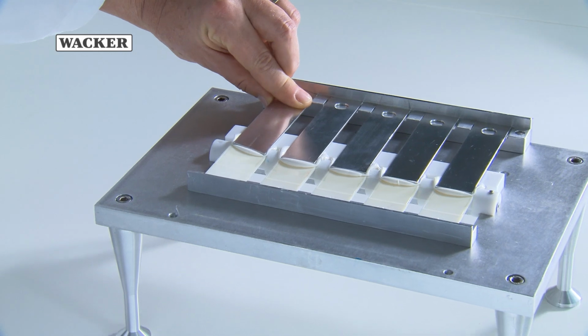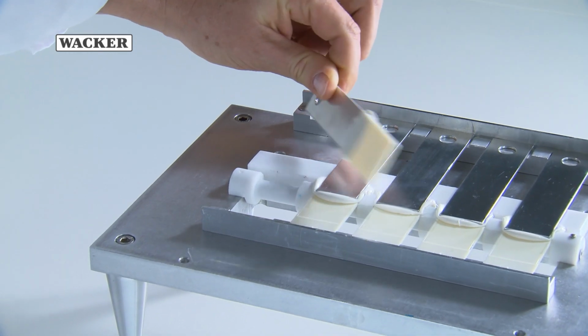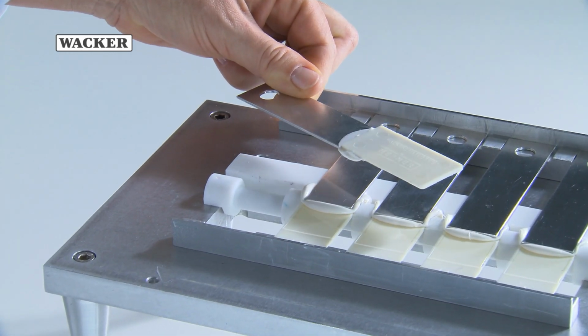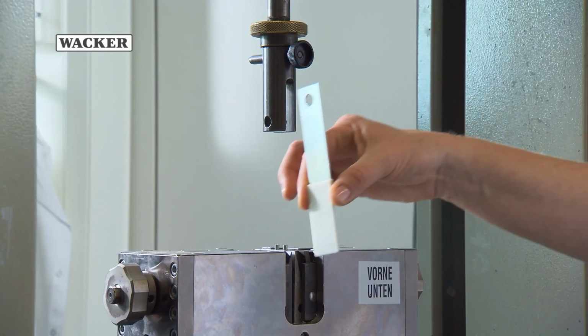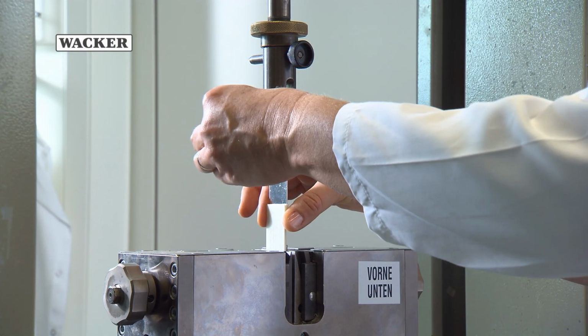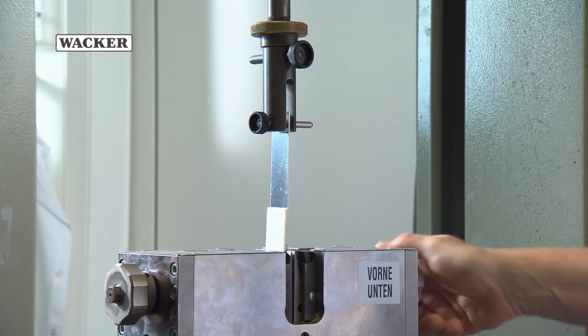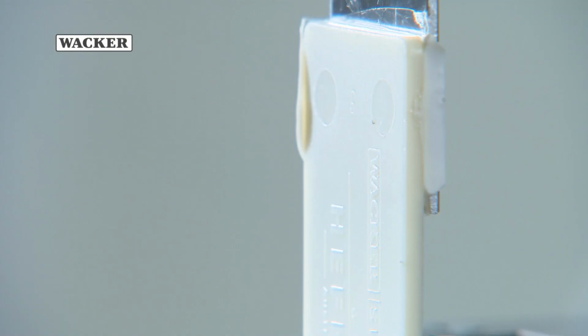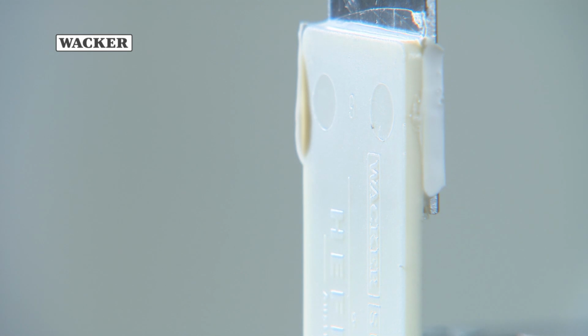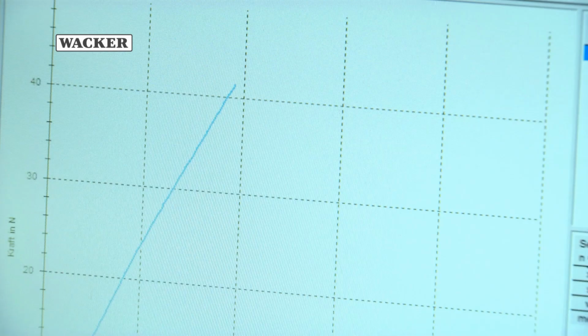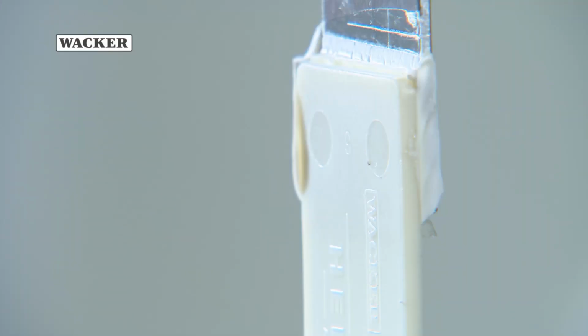Excess material is removed once the silicone, in this case ELASTOSIL N9111, has completely cured. The test specimen is then mounted into the test instrument. The lap shear test measures the force required to pull apart the two test plates in parallel until they are torn off. The maximum required force measured in this way is then divided by the bonded surface area. The result is the tensile shear strength in newtons per square millimetre or in megapascals.